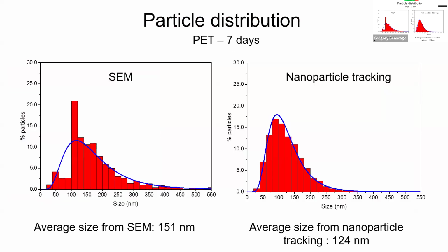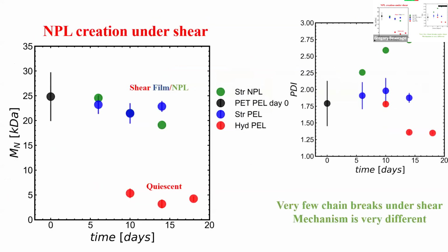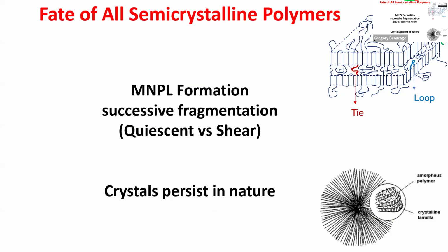Not going to bother with the rest of it. But what I want to leave you with is really this, that this fragmentation is happening because you're breaking bonds in the amorphous phase. Most polymers are semicrystalline. Only 2% of the bonds have to break to make micro nanoplastic. You can continue to break away the amorphous phase. The crystal, nothing is going to happen to it. Nothing is going to go in the crystal and break it up. So this stuff's going to persist for much, much longer than the amorphous phase.